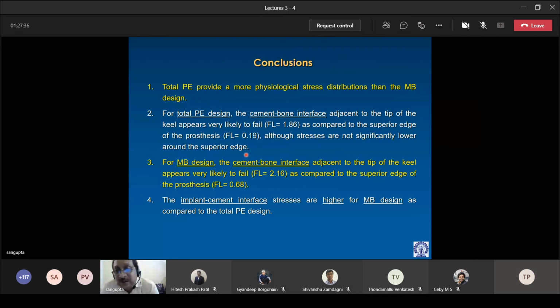So you see that there is hardly any difference in the stress, sigma n and tau, but because the strength is lower around the central part of the glenoid, the local bone strength is lower, even at almost similar values for sigma n and tau, you see the difference in the FL value. So one comes out to be 1.86, the other, superior edge, comes out to be 0.19. So there is no way it can fail there, but this is already a high probability of failure.